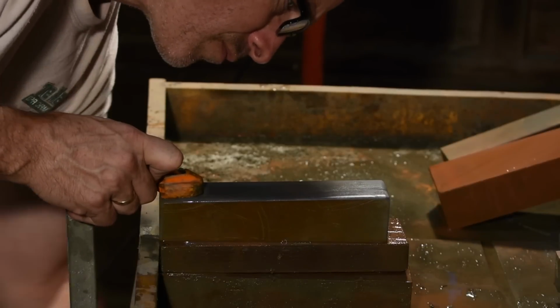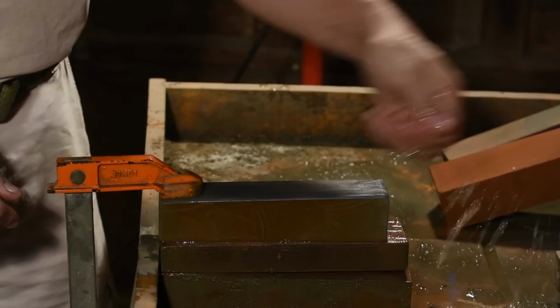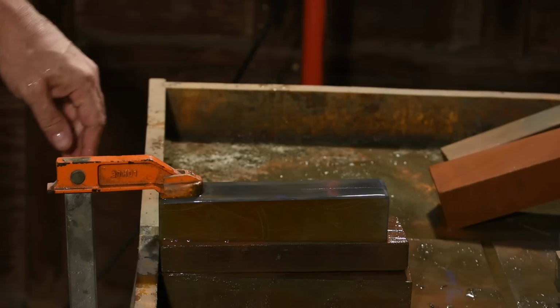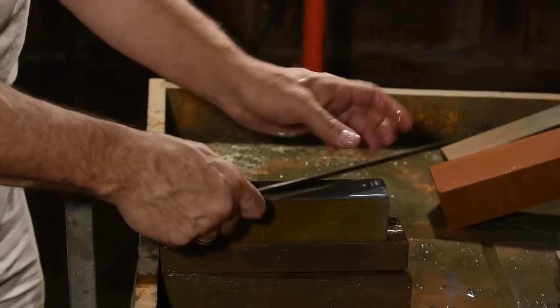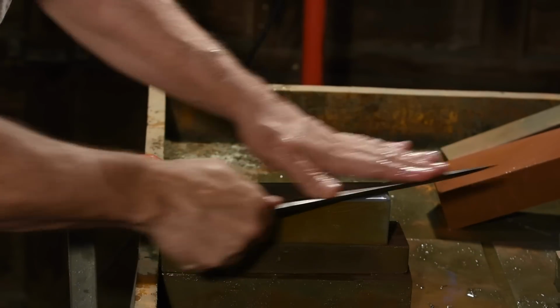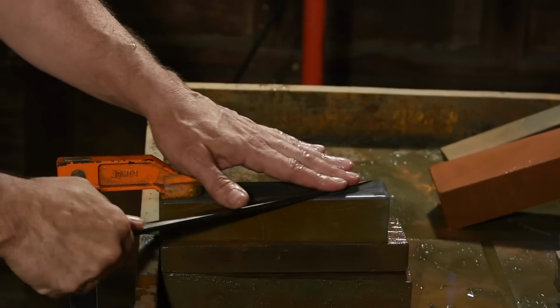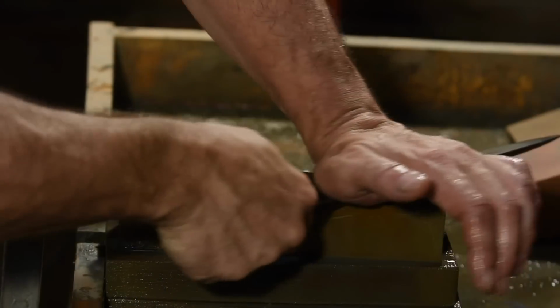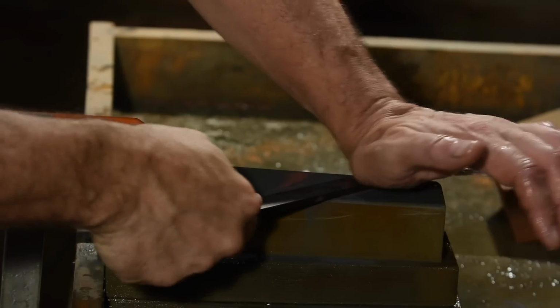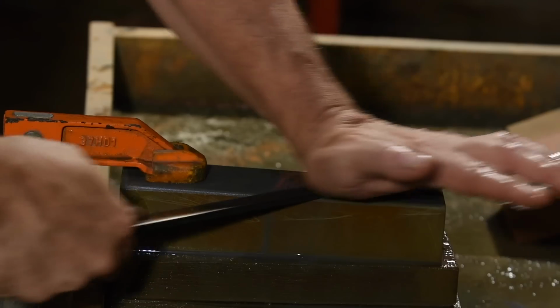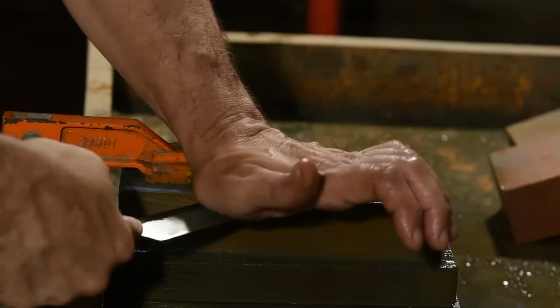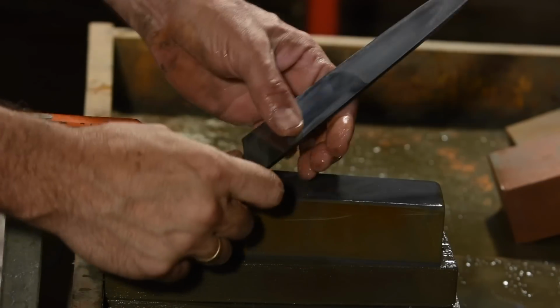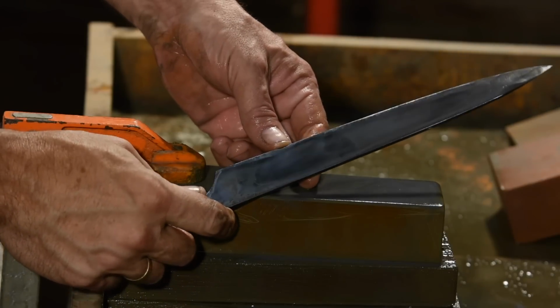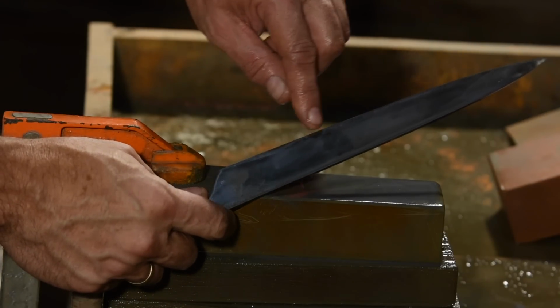So once I've reached a sharp edge, I'll take the knife to my Japanese water stones for final shaping and whetting. Now, Japanese water stones, as the name implies, are kept wet during use. The swarf is washed away and used abrasives wear off rapidly, constantly exposing fresh abrasives so it doesn't clog and stop cutting well. I'll begin with what the Japanese call a binsui stone, which is equivalent to, somewhere in the neighborhood of maybe 300 grit.